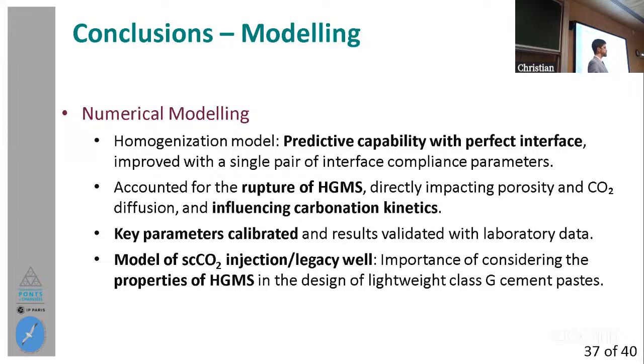And finally, we were able to model the exposure to CO2 in injection well and legacy well conditions. And there we have to take into account the thing that I mentioned before, which is this limitation of not considering the pozzolanic activity and the consumption of the sphere outer part due to the pozzolanic activity.